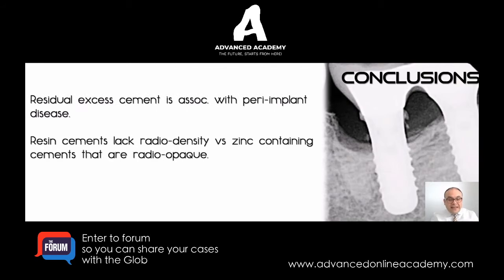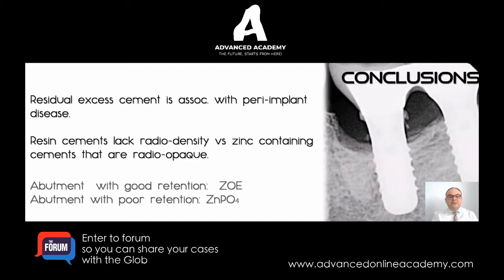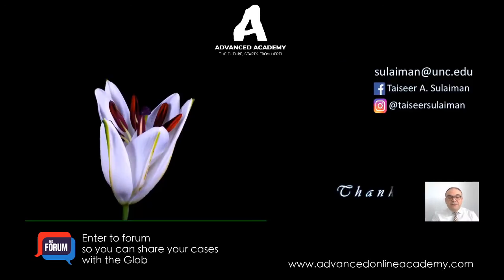Resin cements have low radiodensity versus zinc-containing resin cements that are radiopaque. And then for an abutment with good retention, you can use zinc oxide eugenol. With poor retention, maybe a zinc phosphate cement or something that has zinc in it, so that you can see it in the x-ray and you can clean it properly. I apologize, I went too fast here, but I wanted to include you all.